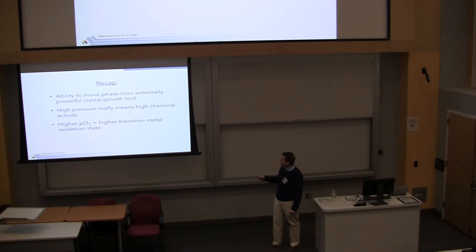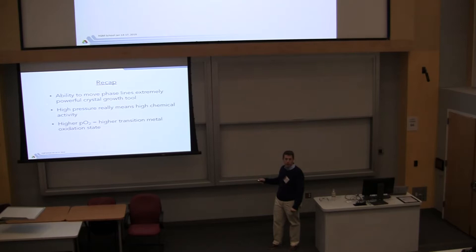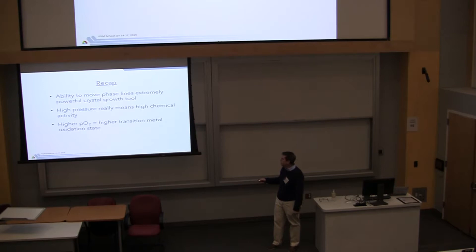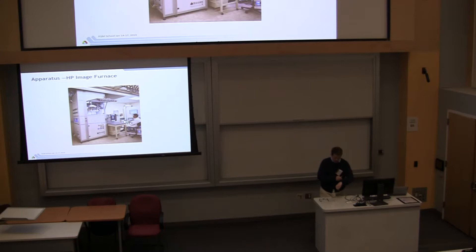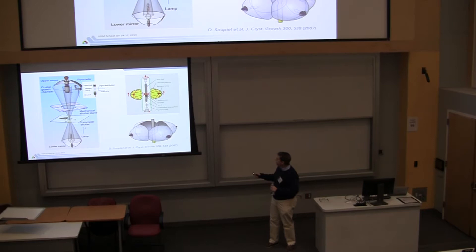So it's not rocket science. Here's an example that you can use the exact same kind of analysis though, not just in solids, but in liquids that melt. So these are some data from, I don't know, 30 years ago, looking at vanadium oxide in the melt. And they actually analyze the concentration of vacancies in this material as a function of the fugacity above the melt. And you can see they form these lines.